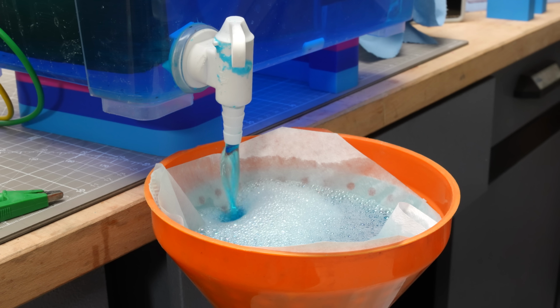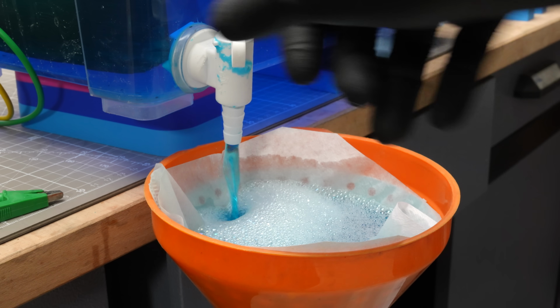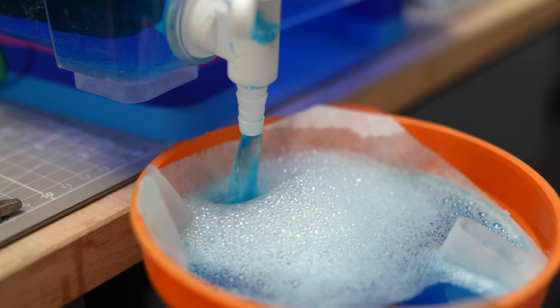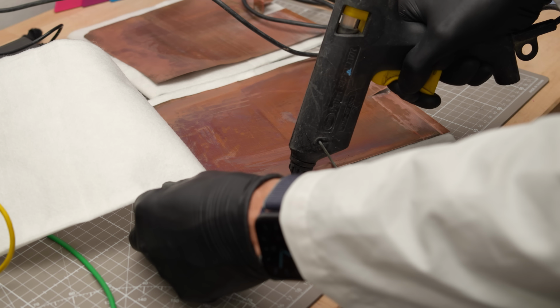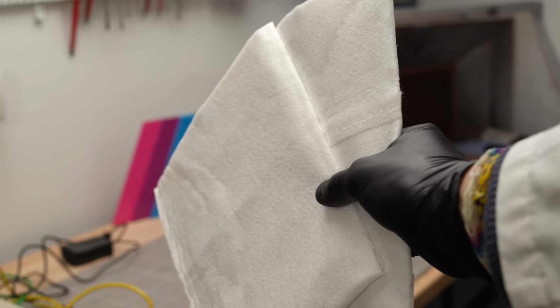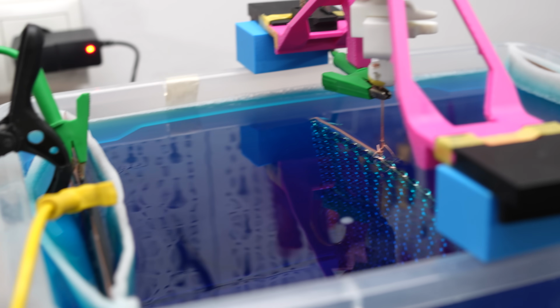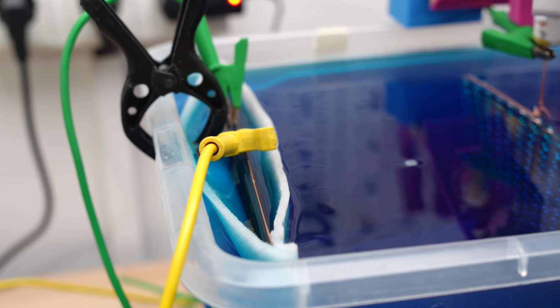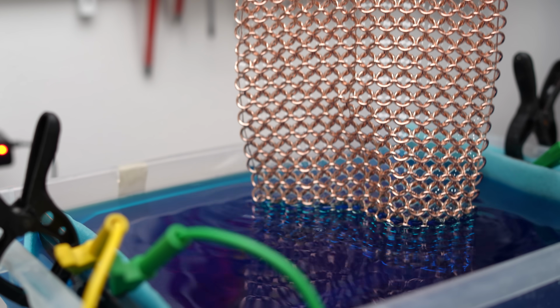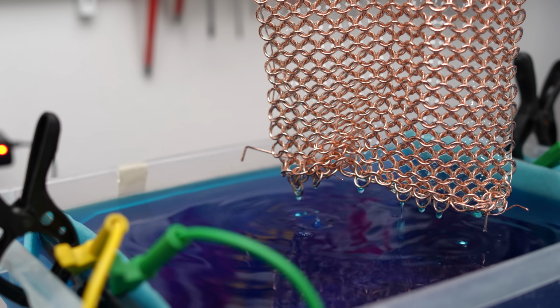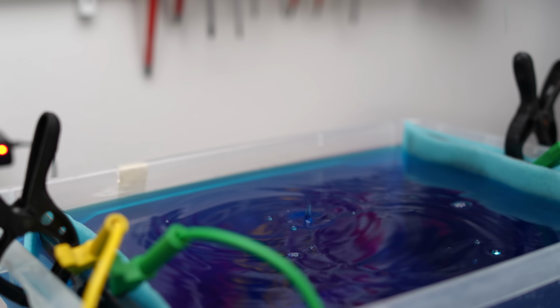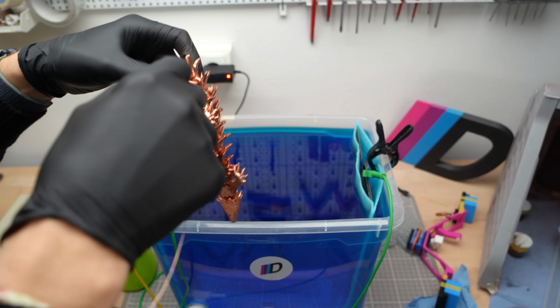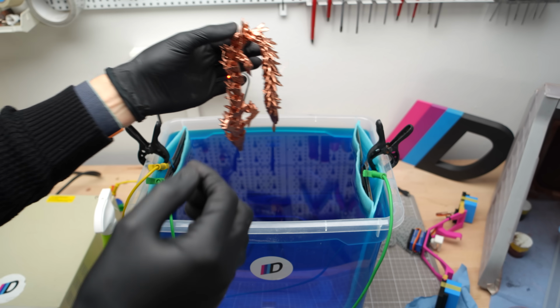Super fail. I need the electrolyte to be as clean as possible. So I pumped everything out, filtered it, and quickly whipped up some filters to match the size of the anodes. Once I had everything back under control, I continued the process. And in the end, I actually got a nice, evenly coated 3D print out of it. Whew! Now it's time for the Flexi Dragon, and honestly, this one gave me zero problems.